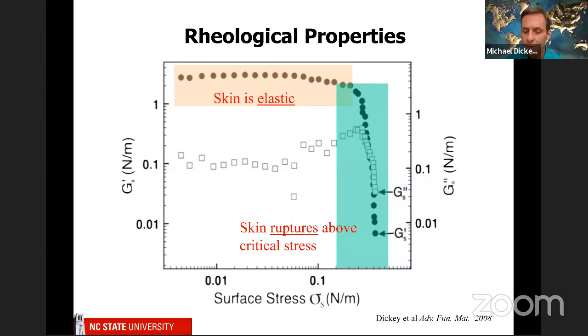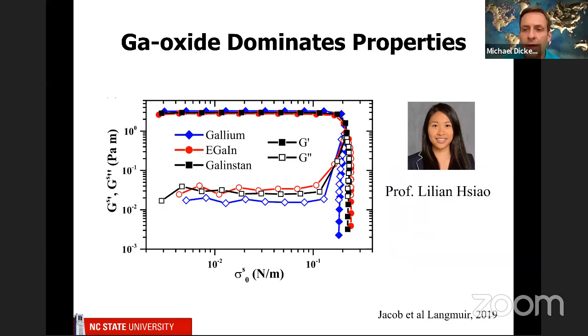Now, in this original work, we only looked at gallium indium, and more recently, one of my really good colleagues, assistant professor here at NC State, Lilian Hsiao, and I worked together, along with some students, to measure different alloys of gallium. So there's gallium, liquid gallium indium, and gallium indium tin, which is called galinstan. And you'll see that all of these things kind of collapse onto the same plot. And this is significant because it means that regardless of what you add to the bulk to lower the melting point, the oxide layer is primarily gallium oxide. So that's kind of the key takeaway here. Now there are exceptions, but in this case, it's gallium oxide.